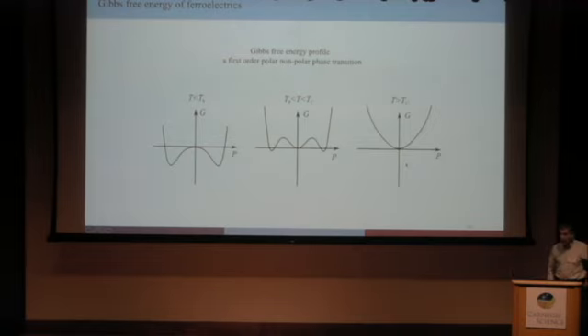Okay, so the basic idea is if you have a Landau-Devonshire model of the energy versus polarization, for very low temperatures, it's a double well. We're very familiar with this. You have maybe up polarization and down polarization. But if you get near the crossover between the polar state and the nonpolar state, the nonpolar state can be a local minimum. It's not favored, but it can be a local minimum. And then eventually you get to a high enough temperature that the minimum at zero polarization is the absolute minimum. And then you're in the paraelectric state. But there's this crossover region where you have accessible to you states with significantly different potential energy.